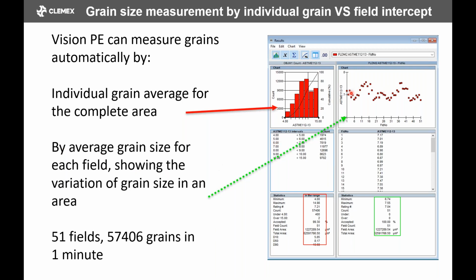At the same time, we measure the grain size by field. Each dot represents a field measurement, the average grain size for that field. When you're scanning, you can see the variation of grain size within your material. Instead of having just the distribution of the grains, this tells you where they are, because you know the field position.